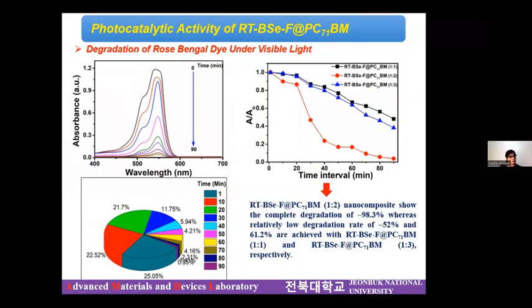And we have found that with the passage of time, the intensity of the UV absorption peak has diminished, it has decreased. And from the pie chart, it is quite obvious that the major photocatalytic activity has been done in the starting 30 minutes. After that, the photocatalytic activity has been reduced.